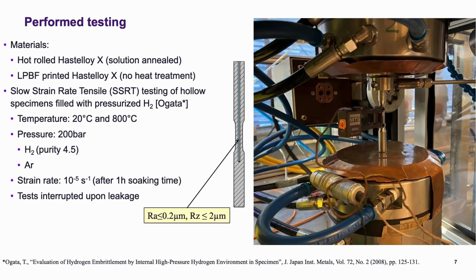And we interrupt the test upon leakage, and as soon as it starts to leak, we don't have any hydrogen anymore, which is important to consider for the high temperature testing. I mean, we measure the hydrogen content afterwards, but if it spends too much time at high temperature after the leakage, the hydrogen will escape in a rather short time. So what we measure after the test could be underestimating the hydrogen content that we actually had upon leakage.